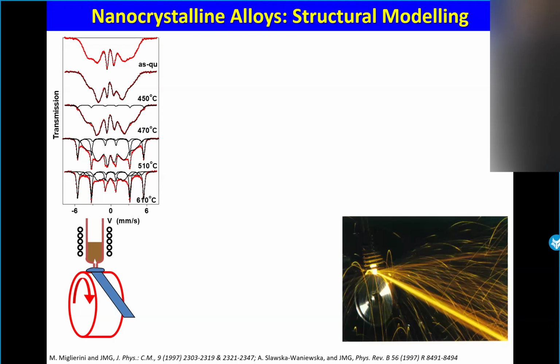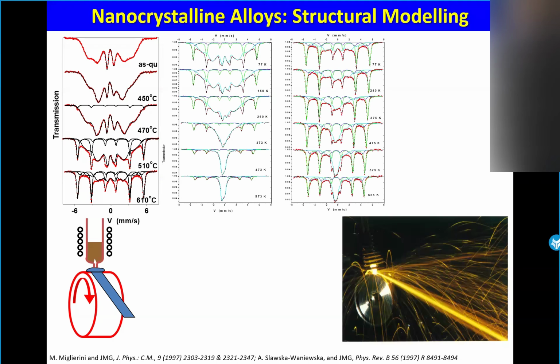And after, at a higher temperature, you will see the appearance of a small sextet. And after it is increasing. Of course, you have some crystalline grains embedded in the matrix. So we made, and it seems to me that we were the only group in the world to make experiments from low temperature up to high temperature to get a pure analysis of all the Mössbauer spectra. If you look carefully, it's difficult to fit the spectra with only 2 components.